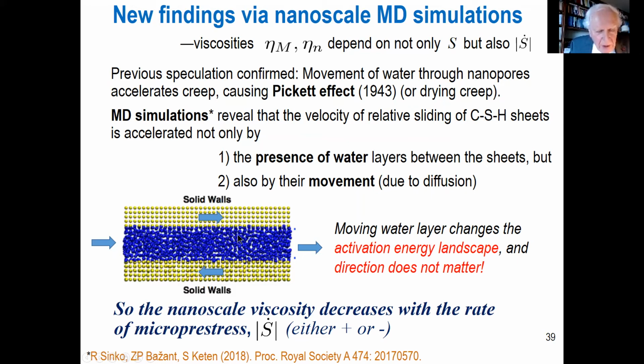Okay, it creeps more, but what is important to recognize is that if we make it move, which would happen due to drying or wetting, it doesn't matter the direction of movement, you get a much smaller viscosity resistance to this force. Intuitively, I imagine there is an energy surface which is wavy up and down, and when the energy surface of one face slides against another, it rides on the tops, so there is much less resistance. It actually comes out from the MD simulations necessarily.